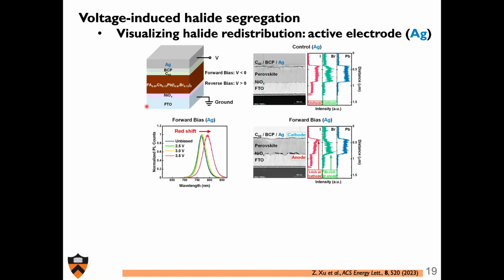Now, what if we change out our electrode? So instead of gold, which is a relatively decent anode in the presence of iodide, it's not readily etched by iodide, if we change it out with silver, again, we have the situation where initially our system is well mixed. Iodide and bromide and lead, they're all evenly distributed. If I forward bias this device, so silver is my cathode, then I get the same situation. Iodide is enriched at the top, bromide is enriched at the bottom. It all behaves very similar to my gold situation.